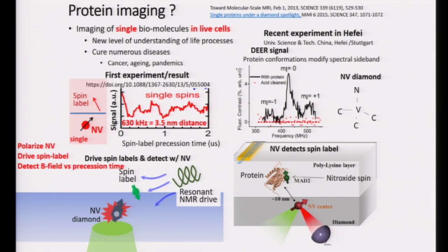Okay, and it happens that between the molecule you want to sense and your nitrogen vacancy, there's a surface. And that surface can have defects, and those defects can have spins. And if they're electron spins, then they're 1,000 times stronger than what you're trying to look at, and they're a noise source blocking you. So you have to get rid of those. And again, by trial and error of 10 years, you know, mostly errors, but lots of trials, we eventually found out that you process the surface in a certain way, and you're able to get rid of most of the spins, and you can start to see things.